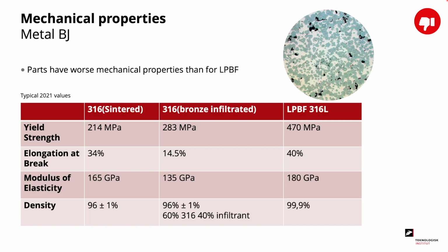Another downside of metal binder jetting is the mechanical properties. Typically the parts have worse mechanical properties than laser powder bed fusion parts. Below I have compared some of the mechanical properties for the same material, 316 stainless steel, manufactured using the different technologies. We find the reason for the much worse mechanical properties in the bottom row, where we see the density is much lower for the binder jetting parts than in the laser powder bed fusion parts.